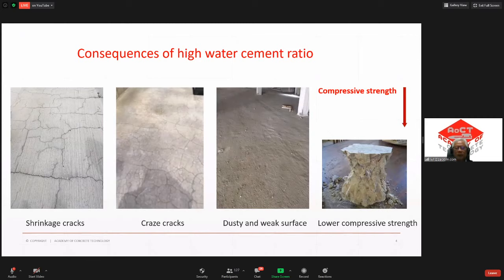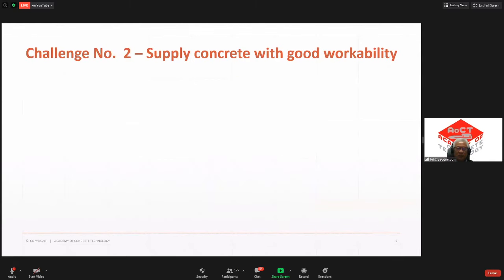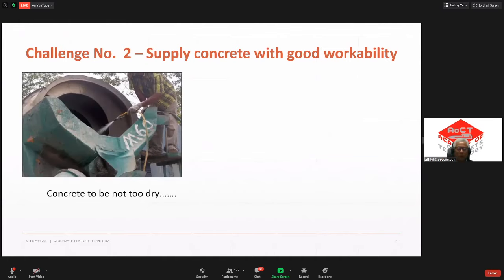Okay, all right. So the second challenge is supplying concrete with good workability. What I mean here is either the concrete is too wet or too dry. You see, when the concrete is too dry, especially you can see from this picture, the workers would definitely have to add water, isn't it? And I always say that if you are a good technician or you know about concrete, it's okay to add water, all right? But you must measure it. Put it in the bucket. If you add maybe 10 kilos of water per meter cube, you might lose probably 2 or 3 MPa, but not using a hose. You can see that this is unlimited, all right? And you don't know how much water you add in and all that. So end of the day, you get a very wet concrete.